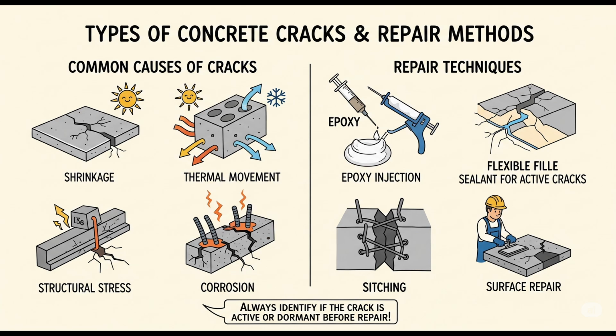Okay, what about the bigger ones, the wide cracks? Especially if they involve problems like rust. Right, for wide cracks, the approach depends heavily on that underlying cause we diagnosed earlier. If the crack is associated with rebar corrosion and rust is clearly visible or suspected, then the damaged concrete cover must be removed to expose the corroded steel. The rebar then needs to be thoroughly cleaned, usually by mechanical means like grit blasting, sometimes treated with corrosion inhibitors, and potentially supplemented if section loss is severe.